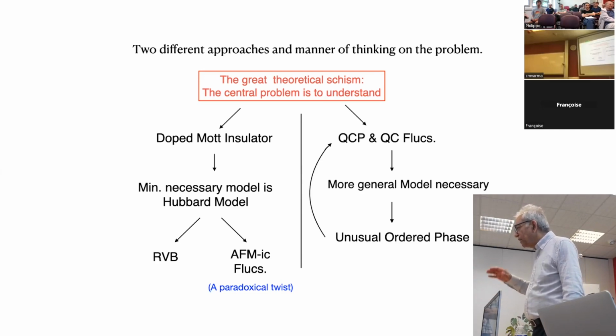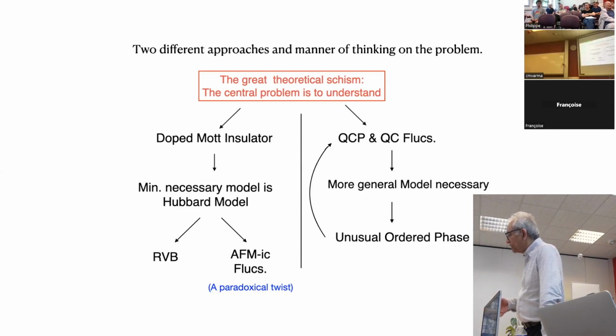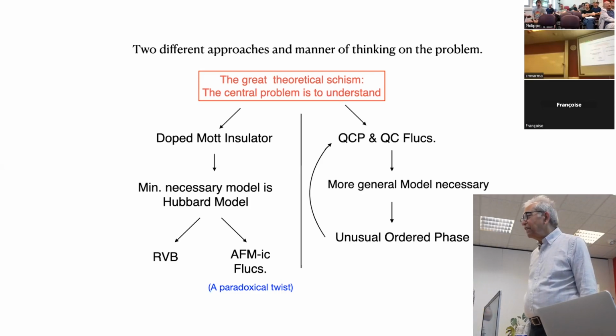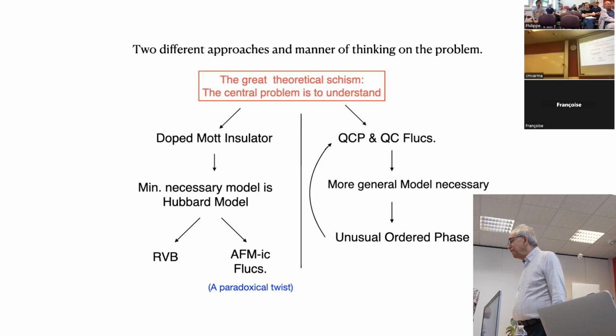I am wondering whether at this level one can say that the pseudo-gap line is really a phase transition, or whether we are pinning something on the disorder and it's not so clear what the situation is. How can you say whether all the sample freezes at the same time? Supposing I look at one of the heavy fermion antiferromagnets, you can see that there is long-range antiferromagnetic order on one side, and there, since the period is changed, one can say more convincingly.